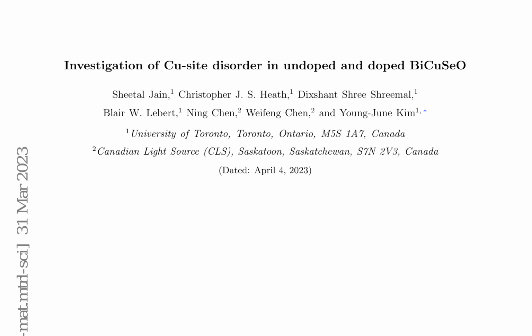Density functional theory (DFT) calculations investigate the electronic structure of the undoped and doped BiCuSeO samples. The calculated density of states, DOS, reveals a significant shift in the valence band edge towards the Fermi level in the doped samples, consistent with the observed decrease in the tetrahedral coordination of Cu ions.